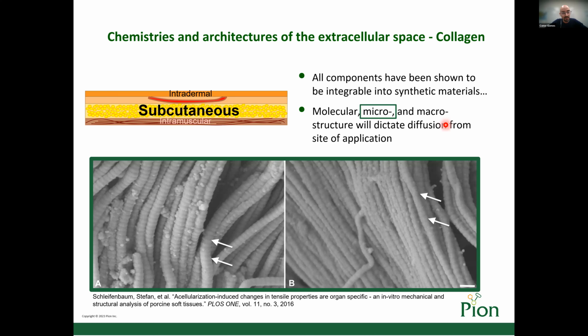An issue is that solubilized collagen is not the interaction that your drug is seeing when it is injected inside a human body. Collagen fibers, these are porcine fibers, slight difference from human, but we can get into that later. These strands are not only going to be organized in a very linear manner, but they're also going to have what's called D-banding, which is each of those tiny little ridges that the white arrows are pointing to. Each of those ridges is going to happen at about 670 angstroms. And if you're talking about diffusion through this space,